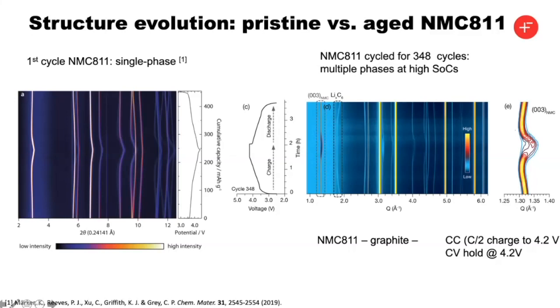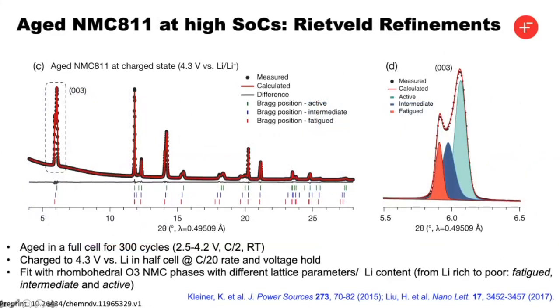And then when you look at the 003, you can see that there's no longer a single phase at these high voltages. Instead, you have what we call the active phase, and then you have a component that's responding much less rapidly. So what Chueh did was then to take the material out of the full cell, charge it against lithium so that he could control the voltages very, very well. And so this is now the diffraction pattern of the aged 811 charged to 4.3 volts. And if you blow up the 003 reflection, which is directly related to the layer spacing, you can see that in order to fit this, we need to invoke at least